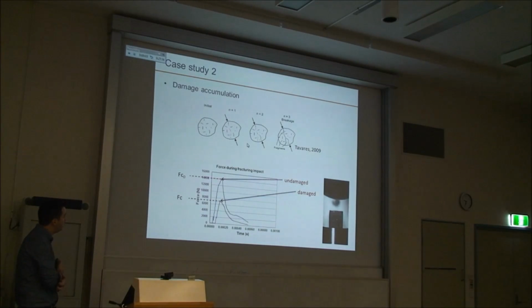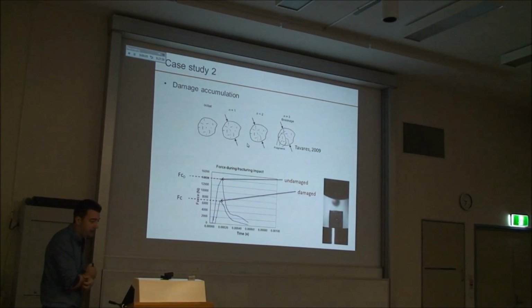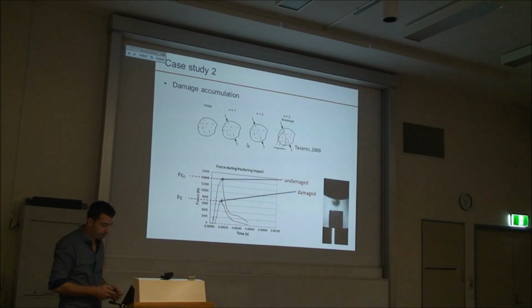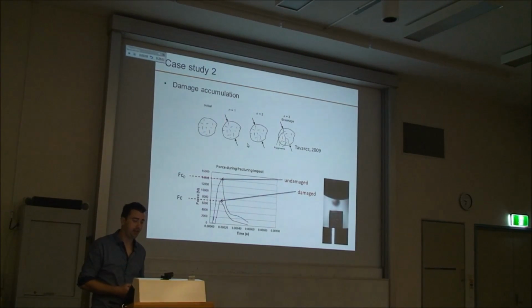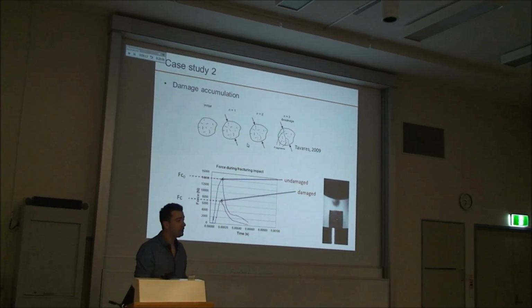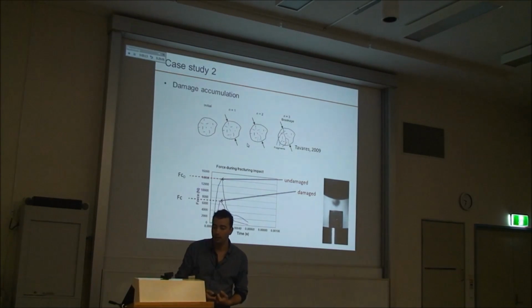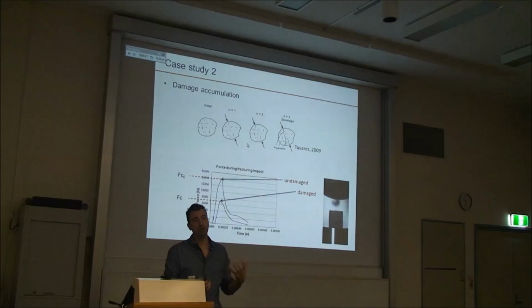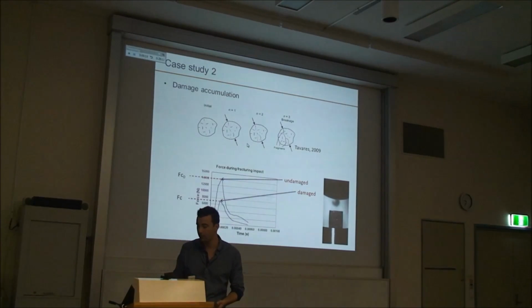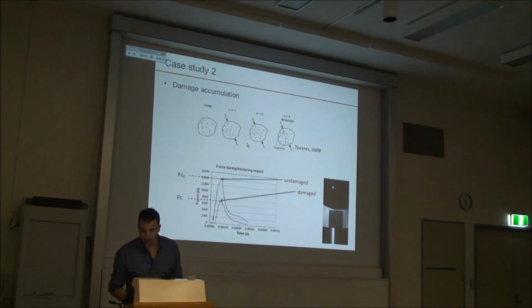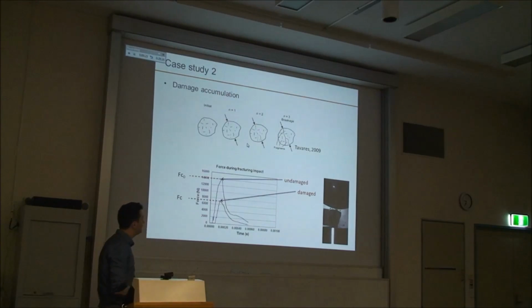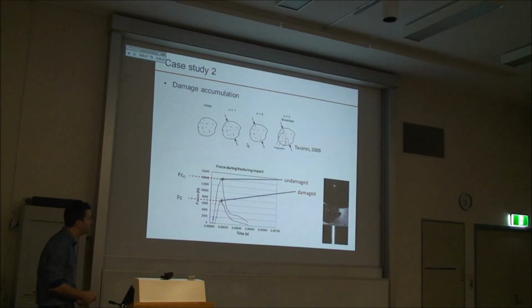In terms of damage accumulation, we also conducted a little study here when we looked at breakage by damage accumulation. So what happens if you have a particle and you impact it, you don't impact it enough to break it, but just to create damage accumulation. So we've impacted cubes. This is a little video of the cubes being broken here on the impact load cell.